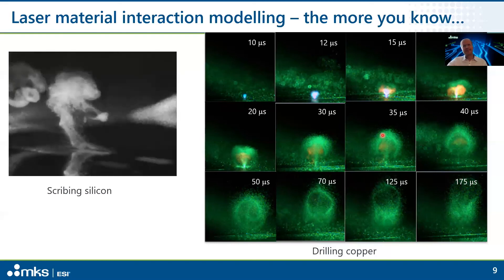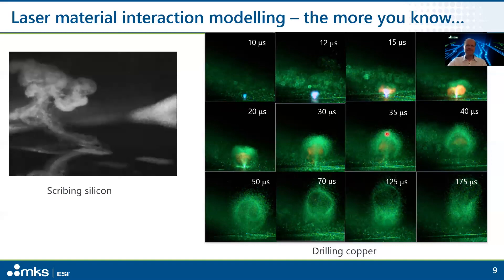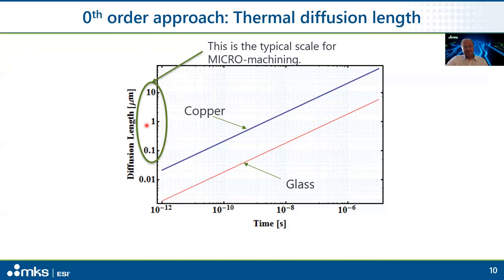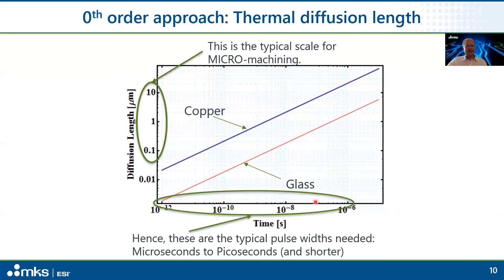The simplest approach on the back of an envelope is to consider thermal diffusion lengths as the characteristic length scale of the heat diffusion equation. Even disparate materials like copper and glass behave within an order of magnitude similarly. For micromachining, the diffusion length is on the order of a micron, so the associated heating timescales range from microseconds down to shorter pulse widths — making intuitive sense that micromachining must happen most of the time with short pulse lasers.